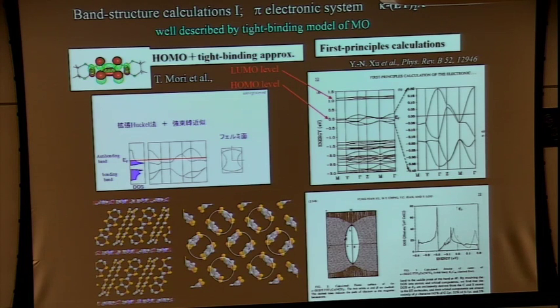This guarantees that you should think only about the HOMO and the HOMO band for the electronic structure. For example, if you construct the Hubbard model or some theoretical model, the first approximation is the band structure. You can start from the band structure of this HOMO orbital, and you can easily calculate it by tight binding approximations based on these HOMO levels. So the band structure is very simple.